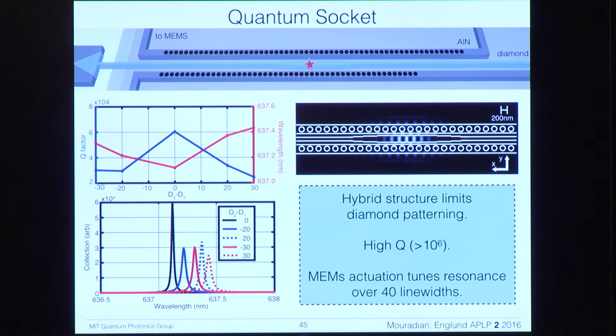So what I showed so far is we have the photonic integrated circuit and we have the diamond, but they don't really interact in any way. But we can also think of building up more complicated structures. For instance, a structure like this where we use aluminum nitride, which has a very strong piezoelectric property, so we could use that to create really hybrid photonic structures. And in this is another photonic crystal cavity. And now we create a band gap. The band gap is created here, so you still see this periodic modulation. But the periodic modulation is happening all in aluminum nitride.